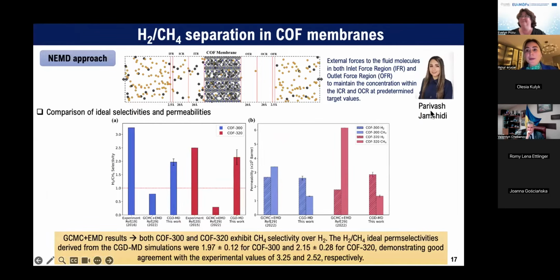Okay. So Parivash, my master student, performed all these simulations. Here, for example, we considered two COF structures, COF-300 and COF-320. These are experimentally well-known COF structures, and we have experimental permeability and selectivity data for these two candidates. What we found is that when you perform the GCMC and EMD method, these materials are methane selective, but in reality, experimental studies show that they are actually hydrogen selective. Therefore, in order to understand this, we switched to the NEMD approach, and when we do modeling with non-equilibrium molecular dynamics, we observe the same trend as the experiments. They are actually hydrogen selective.